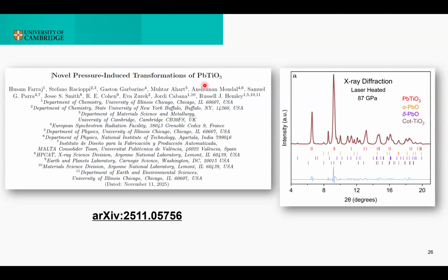And in fact, we have already successfully used this method on multiple occasions, including this recent work done in collaboration with the Hemley Group and led by Hassan, that you can now find on arXiv, in which the powder diffraction assisted search was crucial to identify a series of stable and metastable lead oxide phases formed upon the decomposition of lead titanate.